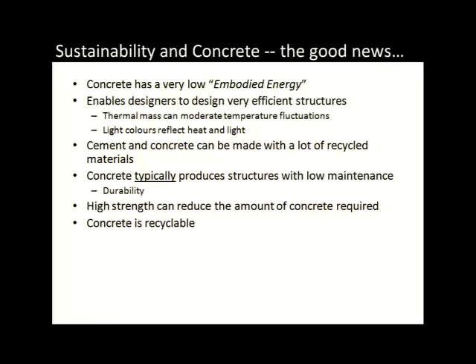I'm going to put a side note down there too that high-strength concrete can actually reduce the amount of concrete that we need in structures. So if we can produce a higher strength concrete, also a higher durability concrete, we can increase the lifespan and the intended use of that, and we can also reduce the amount that's required. The other great thing is that concrete itself can be recycled into new construction materials, whether that's new concrete, asphalt, backfill, insulation, or put into raw feed even for producing new cement.